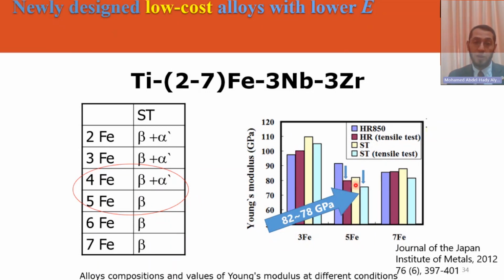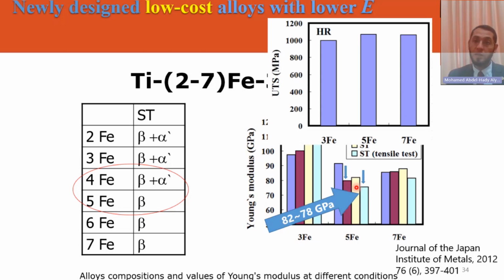Okay, so now, yes, the tool is working very efficiently from the composition. We can manipulate the microstructure. We can control the properties that we need, and the low Young's modulus is achievable. And the strength is still very high for these alloys that have been developed, actually. And this is very good work that has actually been done.